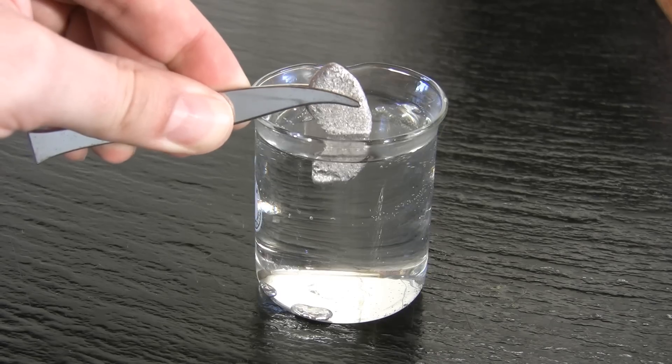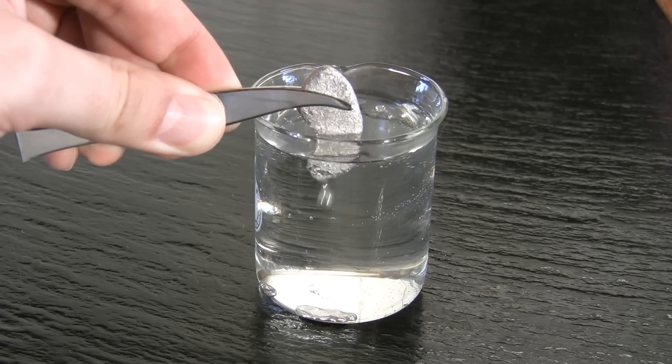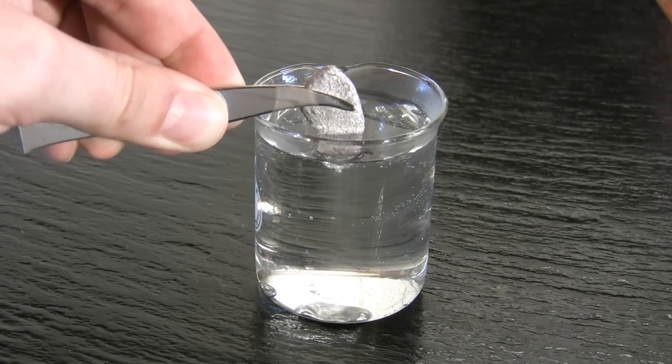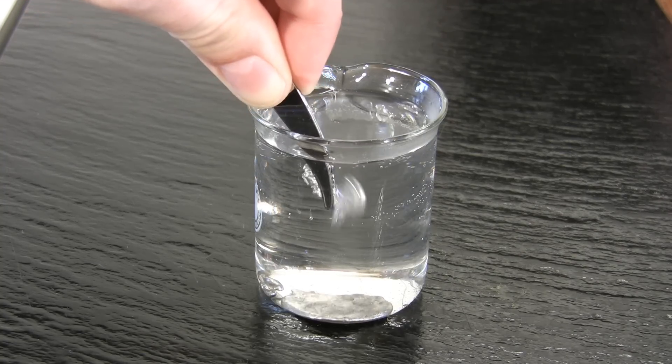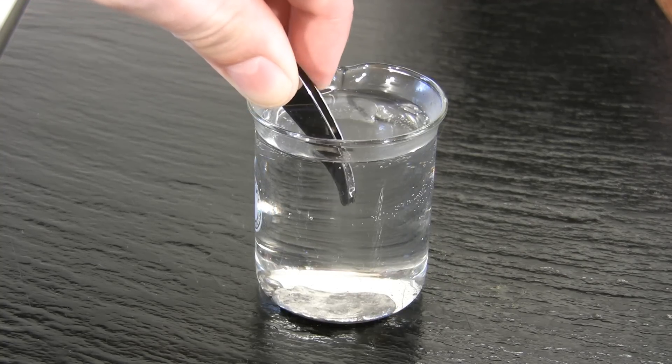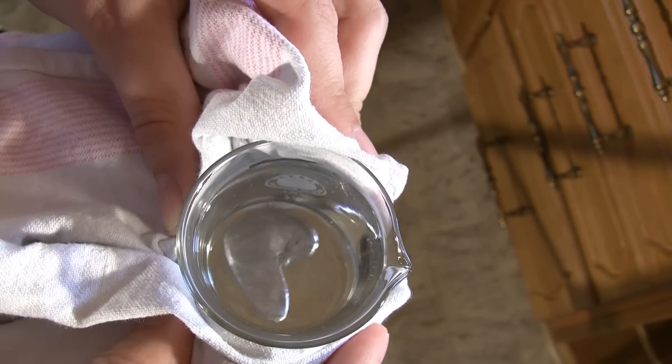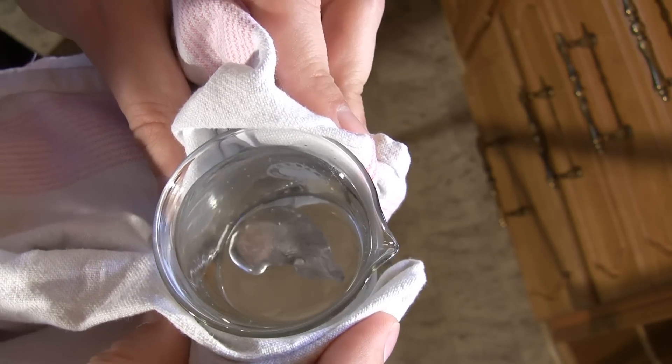This alloy is really easy to melt. No need for near boiling water. My sample is not perfectly eutectic. It is first fully melted at 126 degrees Fahrenheit but isn't completely solidified until cooled to 117 degrees Fahrenheit. In between it's semi-liquid.